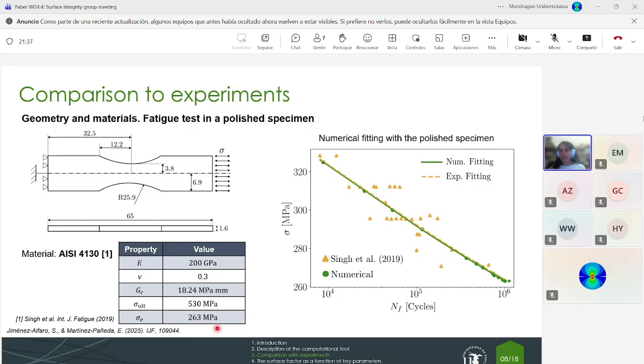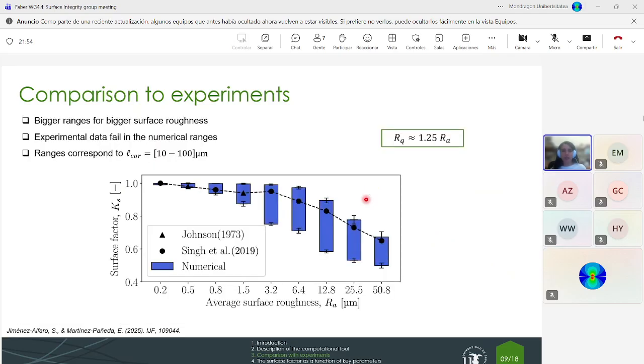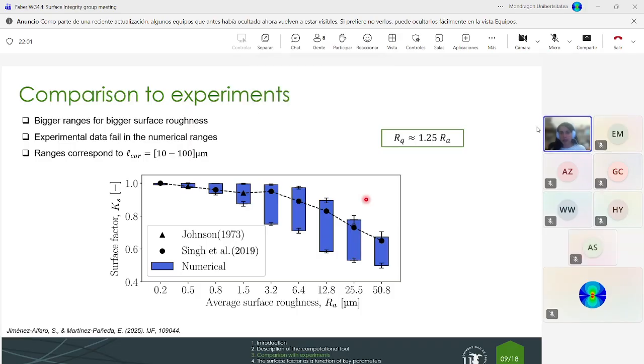So we start with the polished specimen, and we feed our phase field model the different parameters that we have in our numerical framework, using just polished specimens. We ensure that our numerical SN curve fits the experimental one. And now we apply the surface roughness. For that, we have defined the surface factor as a function of different values of the average surface roughness. At this moment, we consider that we don't know the correlation length. We just consider a huge range determined in the literature, as you can see, between 10 and 100 micrometers. This is because a priori in the literature we don't easily find this correlation length. So it is just to see how the computational framework can predict data if we don't have this value.